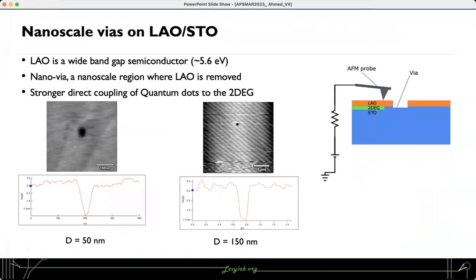One of the main challenges in integrating this system with other quantum materials is that LAO is a wide bandgap semiconductor, so any material that will be placed on the surface will only be weakly coupled to the 2D electron gas. To improve coupling through direct contact, we propose creating nanoscale vias where we etch the lanthanum aluminate layer to allow direct contact with the interface. We can create these nanovias with sub-50 nanometer resolution.